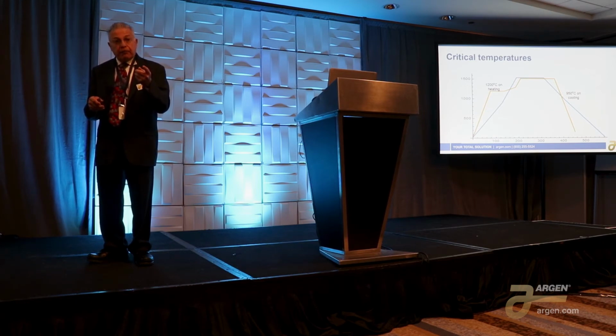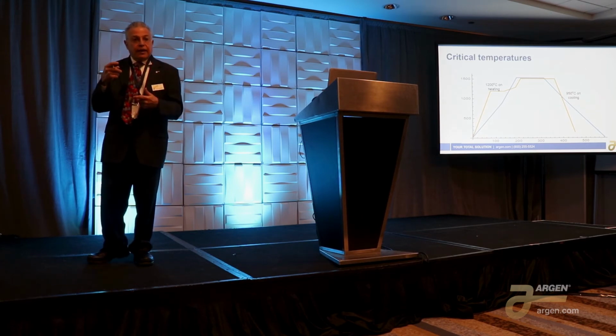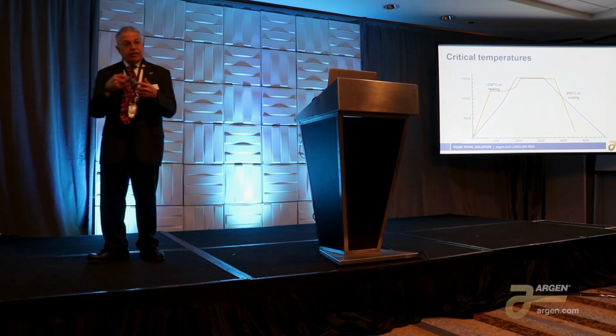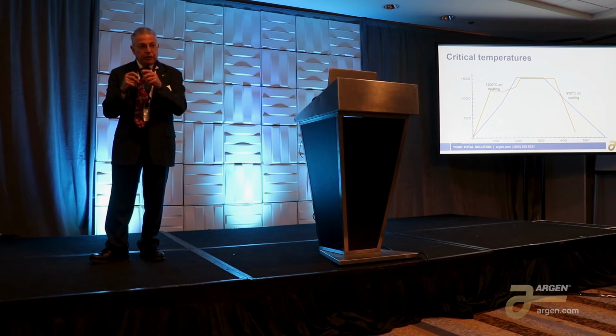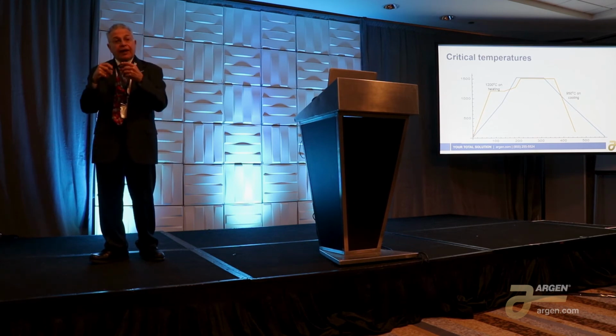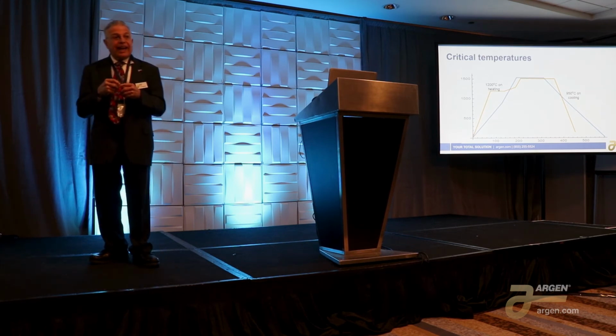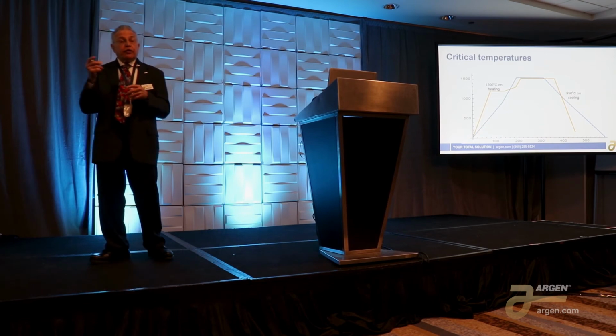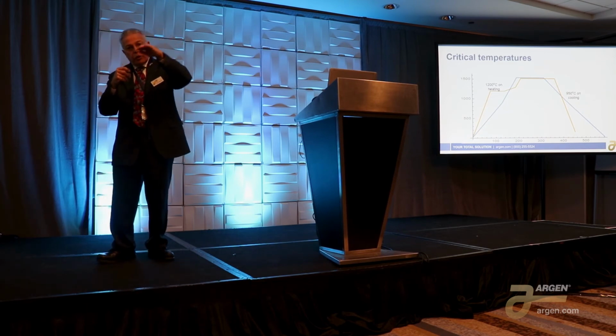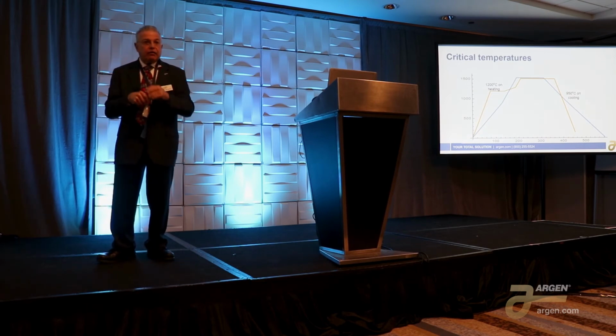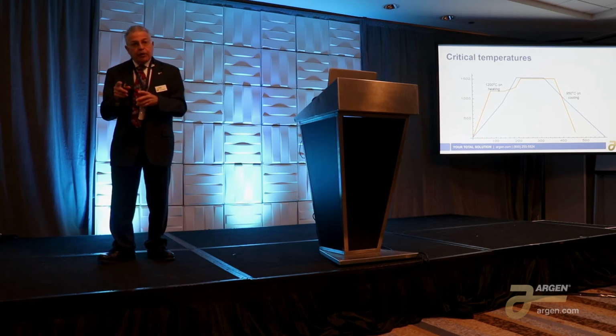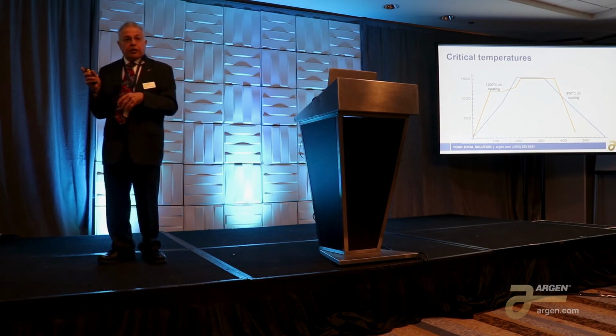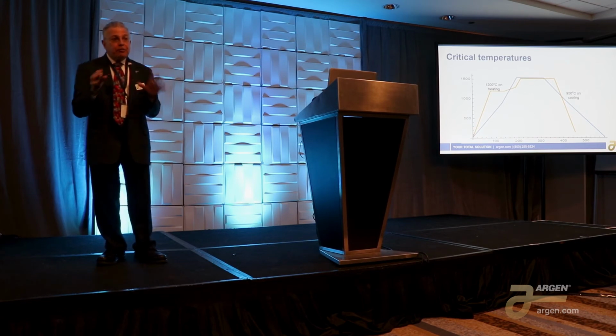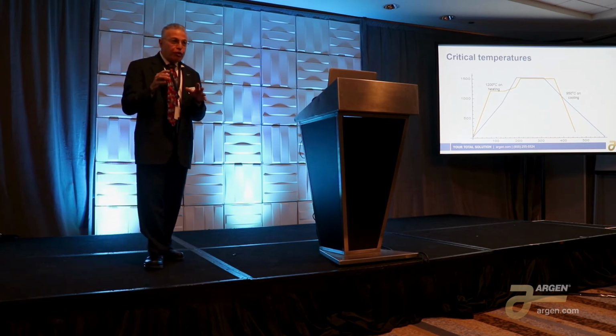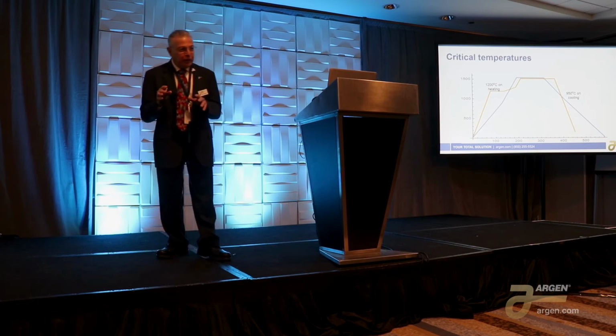It would be opaque. Because there's a transformation that happens to the cubic zirconia that's in the material, and that affects the translucency to the negative. So now you develop the translucency, then you lose the translucency as you go higher in temperature. So you have to be very careful when you sinter the zirconia. You have to do something very dramatic. You actually have to read the instructions. And just try and follow the instructions a little bit, okay?